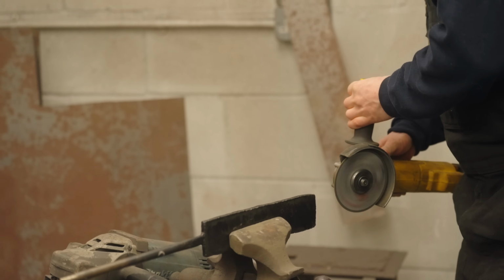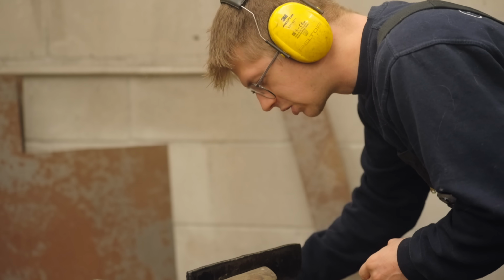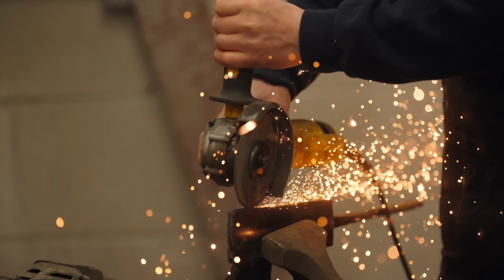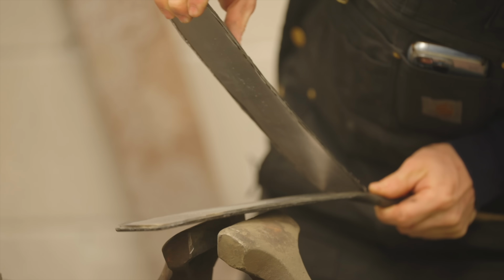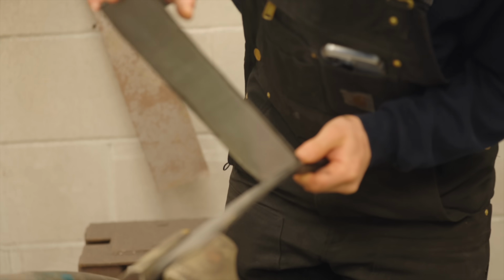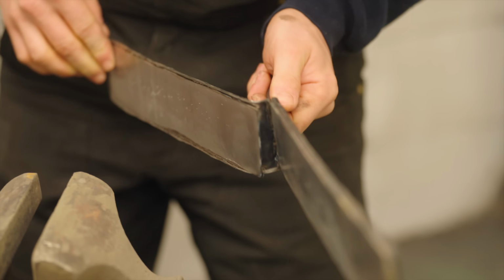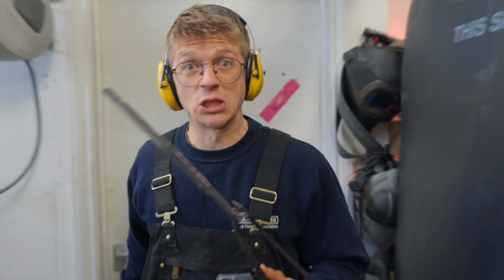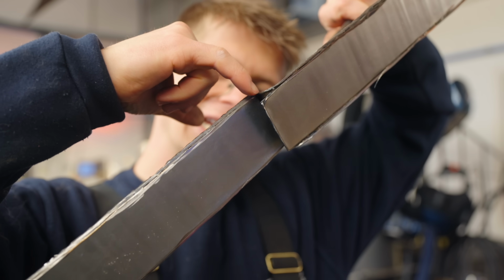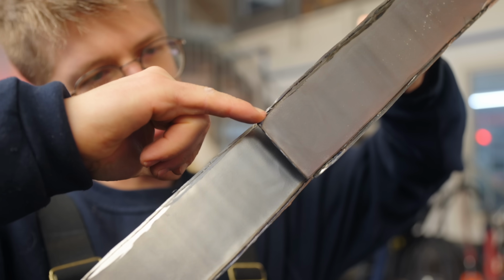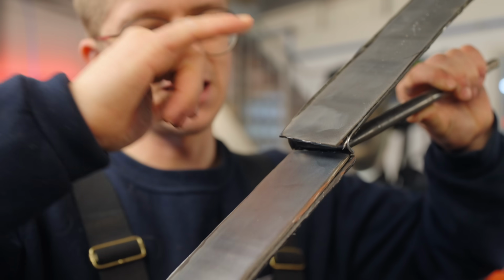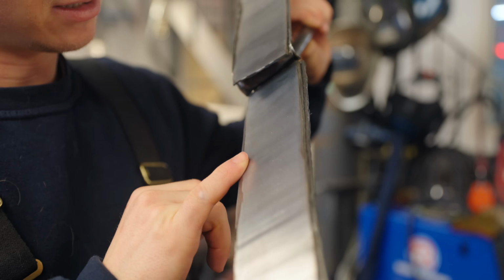Whoa! Something just popped. I really hope that was the jacket that just popped. Please tell me it's good news, not bad news. Ugh! No! Bugger! The steel didn't bond to the titanium. Not good, guys. I'm seeing jacket from the box bonded to the titanium more than the titanium bonded to our actual steel. Oy. Both sides of the billet didn't bond to the titanium.